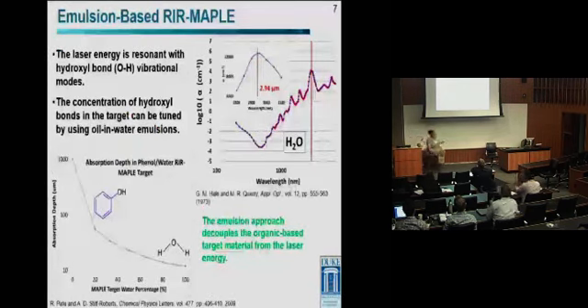So the general idea then with this emulsion, our matrix, what's the matrix that we care about? What's been unique with our approach is that we're using these emulsions. And so the peak laser wavelength at 2.94 microns is resonant with the vibrational modes of OH bonds. And so what we've decided to use as our matrix then is water, which is why we make emulsions. This actually gives us a lot of versatility because we can use any target material, whatever solvent it likes best, and make an emulsion with water. And so in this way, we decouple the laser energy from the material that we're depositing. That's given us a lot of versatility in terms of the range of materials that we can deposit.